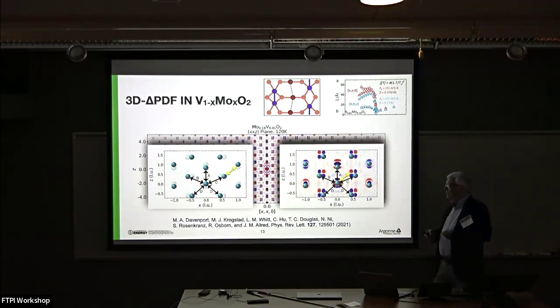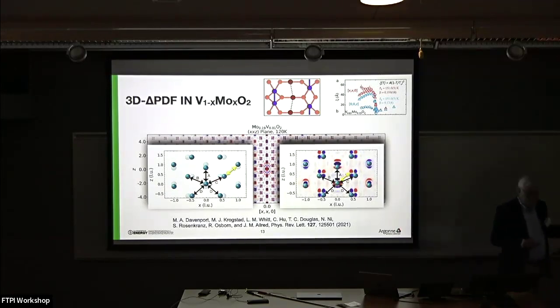So what we have is a strongly first order electronic phase transition. We have local lattice distortions that accompany that transition, but they never become long range. They only remain short range. And there's actually been a lot of thin film work, for instance on VO2 thin films, where they claim there doesn't seem to be enough lattice distortion at all. And that's because I think the techniques they're using are only sensitive to long range distortions, and these thin films are only short range.